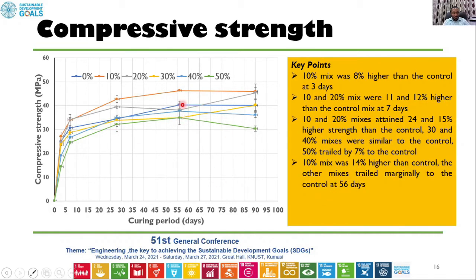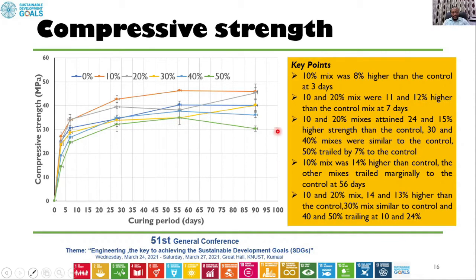So what is happening at 56 days? At 56 days, we also realized that it was only 10% that was higher than the control, but then the 30 and 40% were marginally lower than the control mix, and then you will see that 50% was also lower than the control mix. And then at 90 days, the 10 and 20% had a superior strength than the control. But you can also see that the 30% concrete mix was almost the same as the control concrete. However, 40 and 50 were all lower. They were trailing below the control.